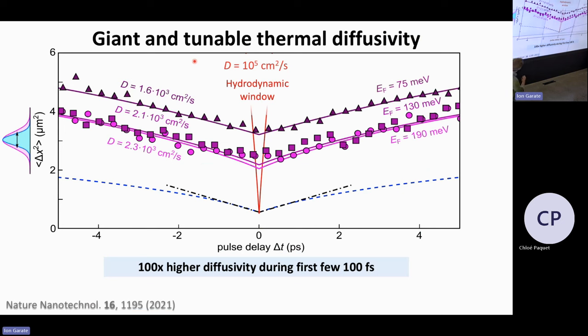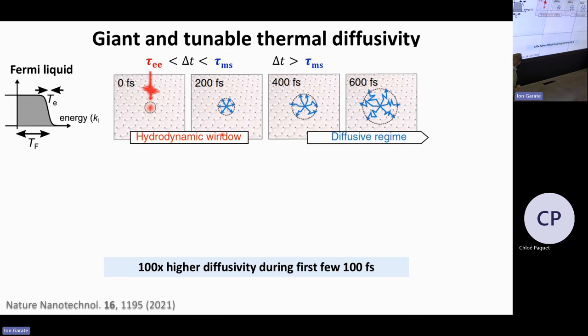So we can plot here indeed a diffusivity of 100,000 that lives just for a few hundred femtoseconds. And then indeed you end up with a starting point that's somewhere here. So we cannot resolve this dynamics exactly, but instead what we get is a higher begin point around time zero. And this explains why in this measurement where we had a lower Fermi energy, we indeed start at a higher starting point. So we then end up with the following picture.